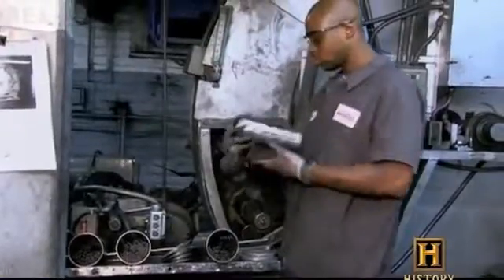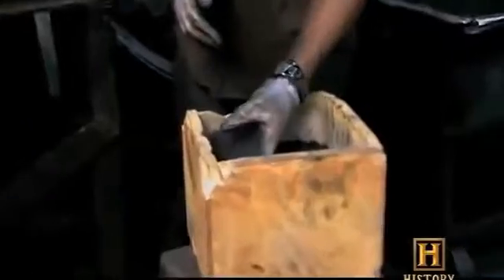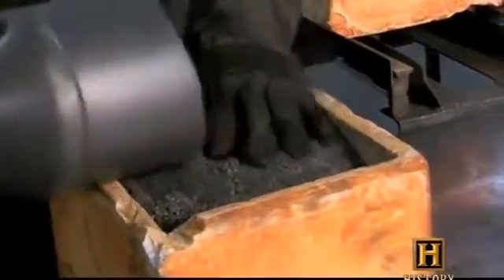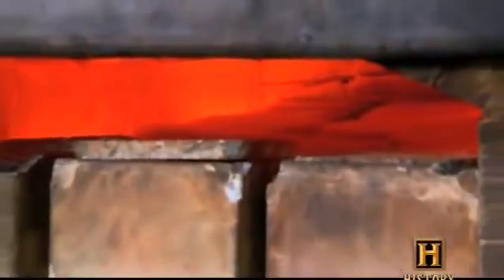Once the pencil cores are extruded out and dried, they're placed into the crucibles which we're actually going to put into our furnace. On top of the crucible, we pour a packing graphite to make sure that the oxygen doesn't get down to leads, the cores themselves, to burn out that carbon. While the 1800-degree furnace stiffens the leads,